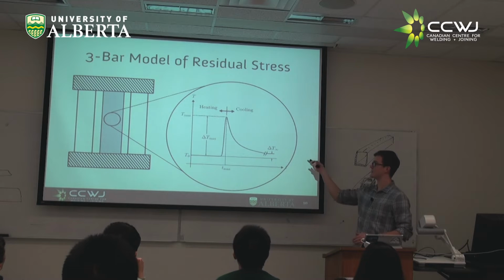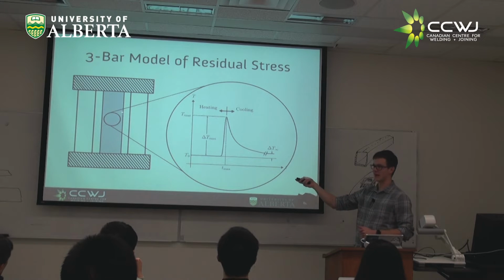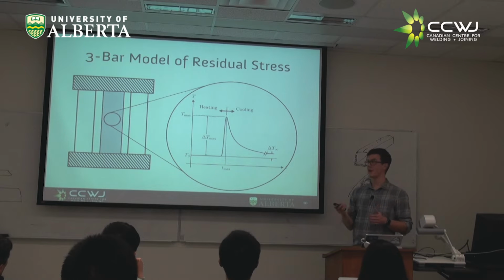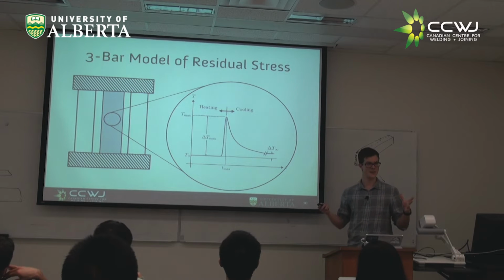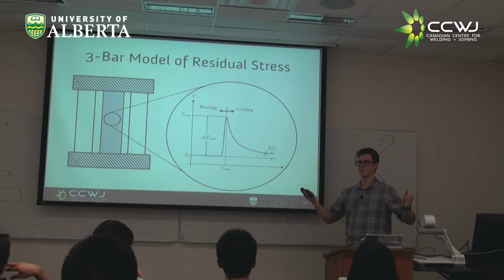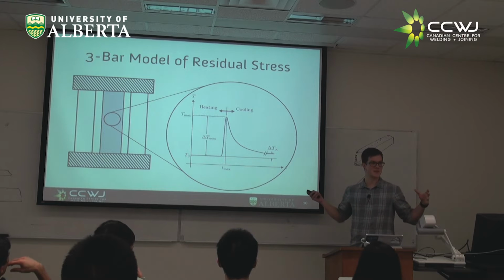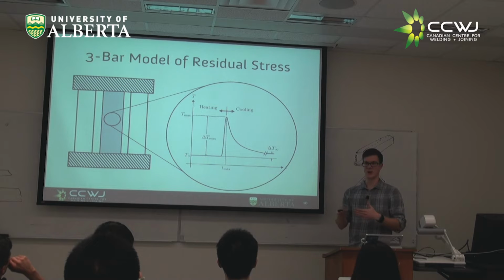And all the complexity we see in the temperature distribution of welding, all of that is happening in this middle bar. This doesn't look a lot like a welded plate, but think about it for a second. When you weld, you've got some region away from your weld that is not affected by welding, at least not at the time you're worried about. If you've got a big enough plate, near the weld you've got temperature and stress, but really far away, that temperature is not going to reach there. So the only thing that can happen to that region far away is some mechanical effects of your stress. If you have stress near the weld, those mechanical effects can propagate differently than the thermal effects. Does that make sense to everyone?